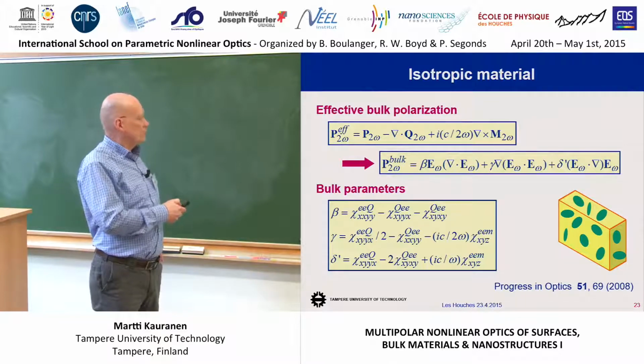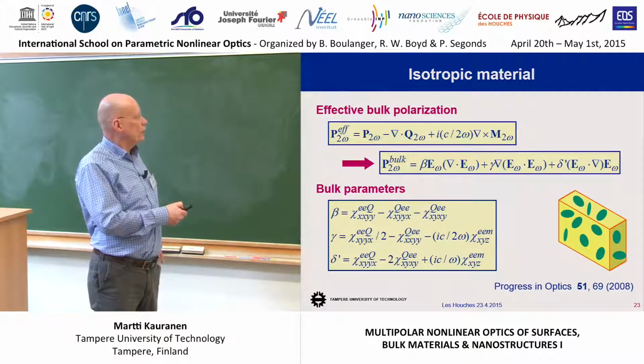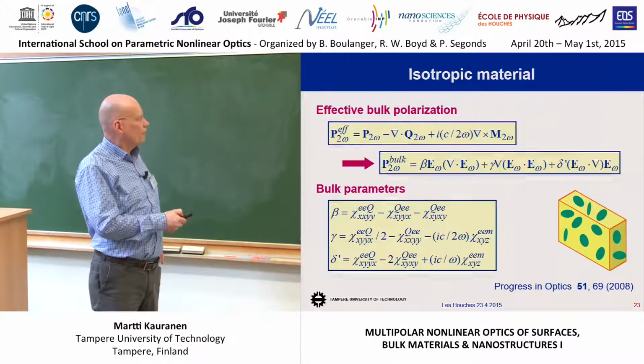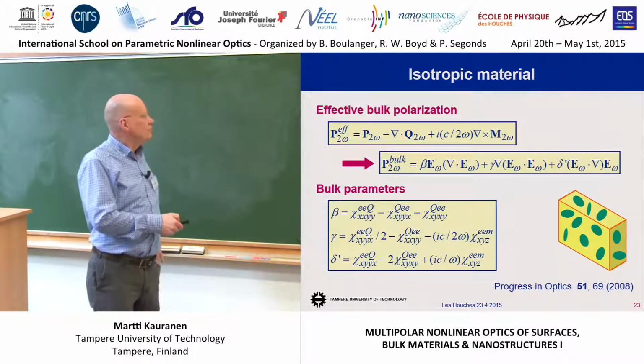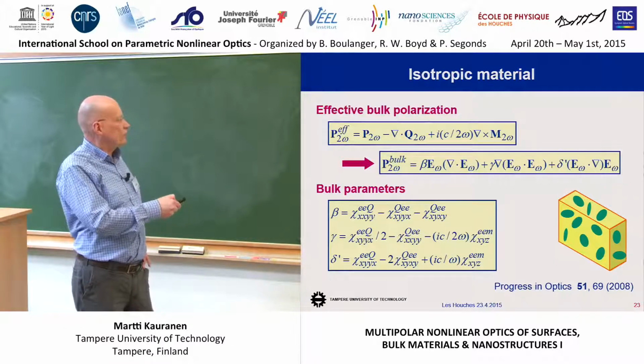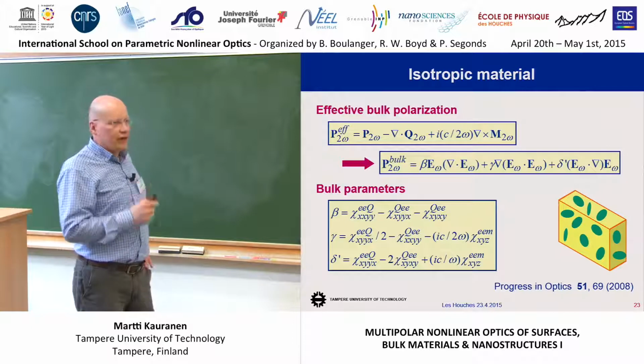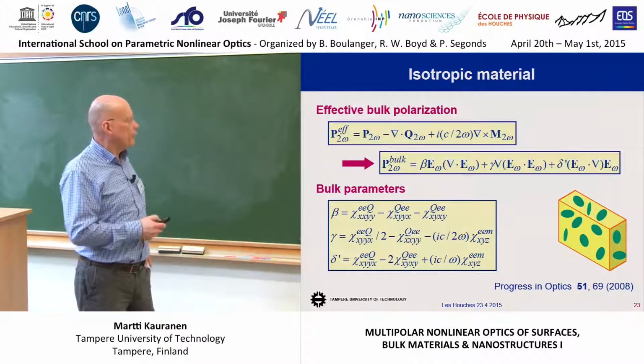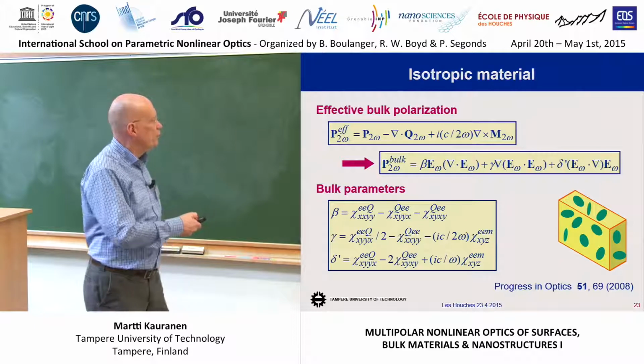So this effective polarization includes the true dipole polarization. Then it depends on the quadrupolarization, so you have to take the dot product of the quadrupole tensor with the gradient, and then you have the magnetic sources here, so you have to calculate the curl of the magnetic sources. And then when you do a few pages of calculations from here to here, you find out that your effective polarization can be expressed in this very generic form.